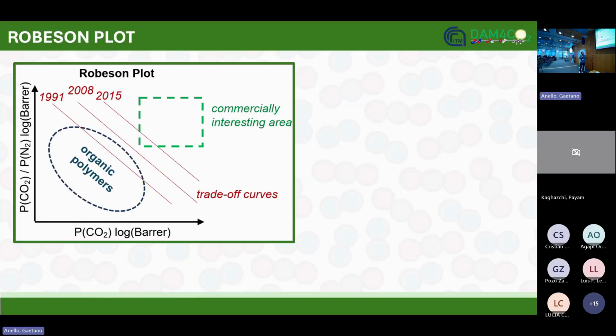So if we put them for each membrane in a logarithmic scale scatter plot, you can see here on the x-axis the permeability and the selectivity on the y-axis. And we can see that organic polymers cluster in a region, which is not very interesting because we are interested in the one highlighted in green because they show high selectivity and high permeability at the same time. And you can see that there are some trade-off curves because usually when you modify the membrane structure to increase the permeability, you have a decrease in selectivity and vice versa. So each year that is indicated, the trade-off is defined by the most promising materials.